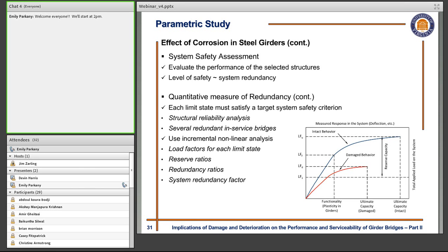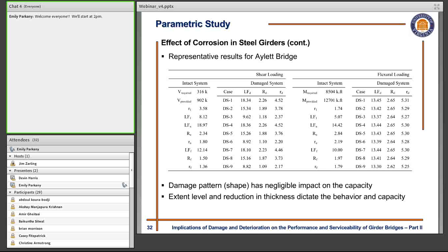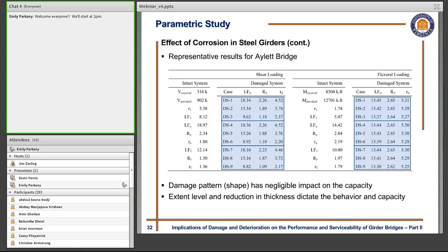So these are the limit states, and for each of these limit states they defined some target values. They defined those target values based on the reliability analysis that they performed on a series of hundreds of structures in service that are believed to be redundant structures. So comparing the loads according to each of these limit states that we define from the numerical analysis to those target values, we'll have the redundancy ratios. Comparing these redundancy ratios with the reserve ratio of each of the members of the structure, we'll have the redundancy factor of the system, which gives us an idea of the level of safety of the structure under the effect of any type of simulated damage.